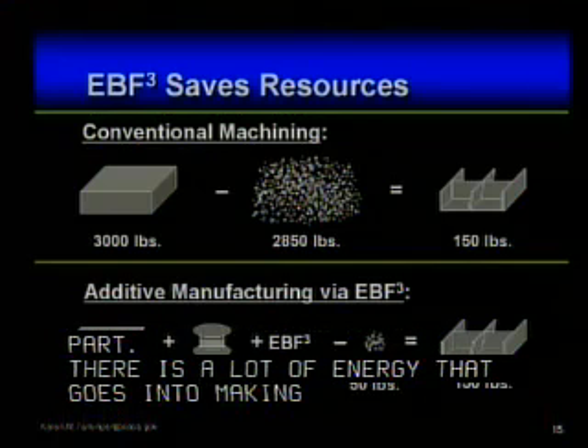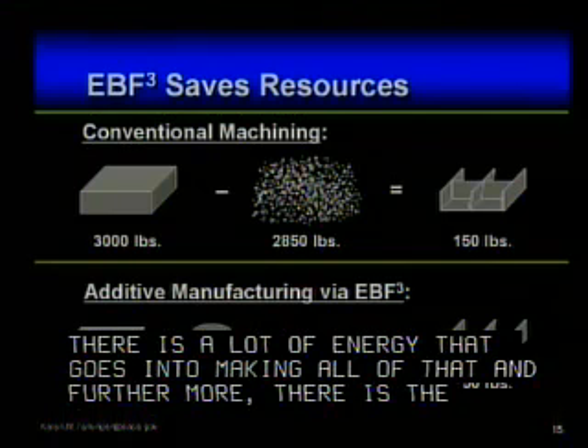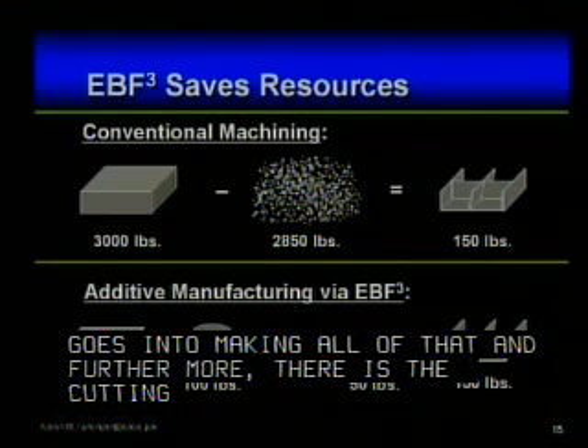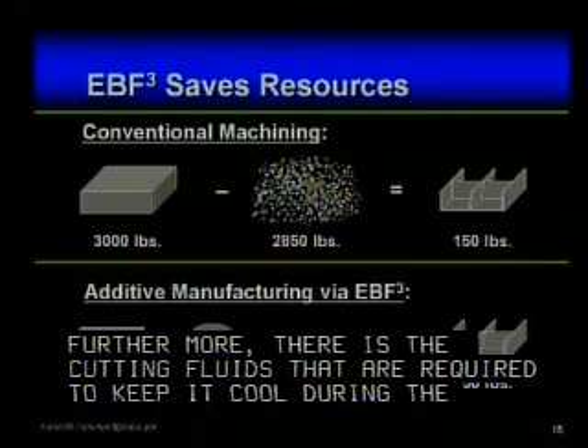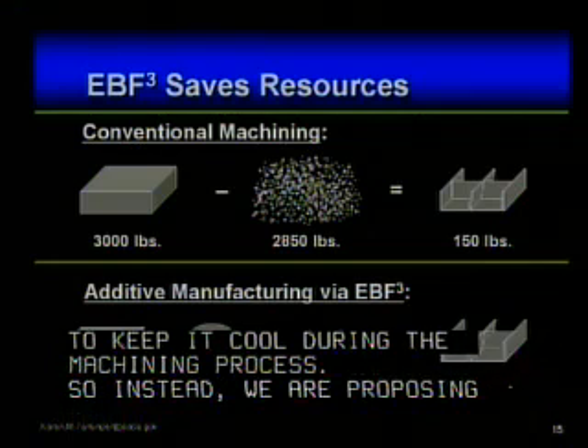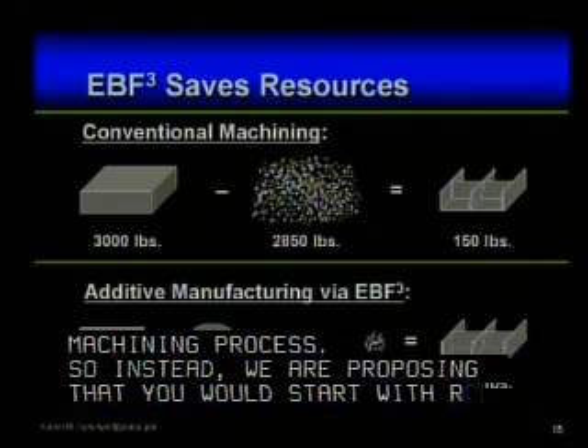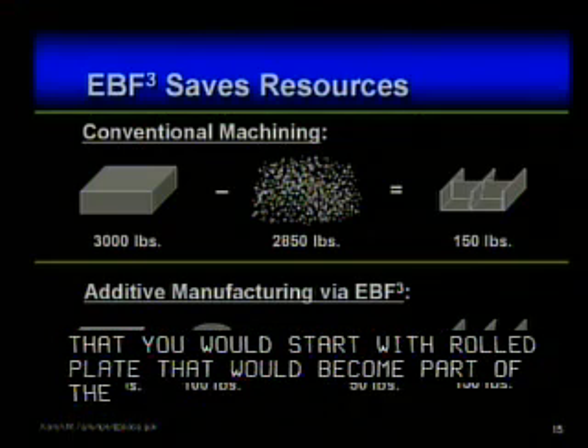And furthermore, there's all the cutting fluids that are required to keep the part cool during all of that machining operation. And those cutting fluids have to be handled as hazardous waste at the conclusion of the process. So instead, what we're proposing is you would start with a rolled sheet or plate that would become part of the process, or part of your final part, and then use the wire feedstock with the EBF³ process to put the material where you need it.